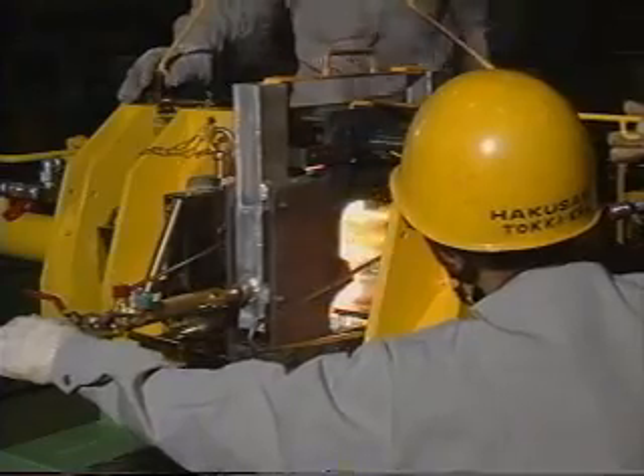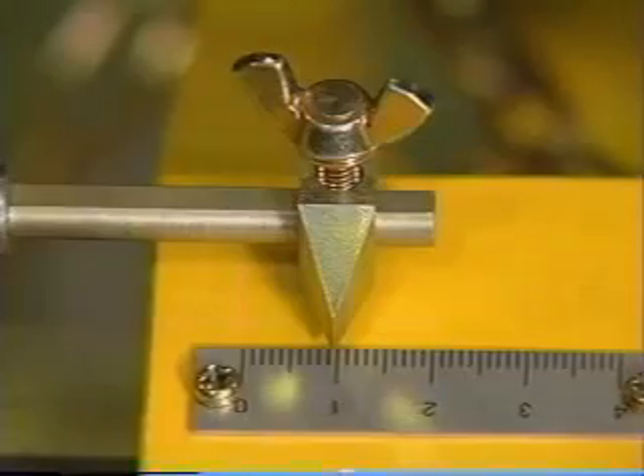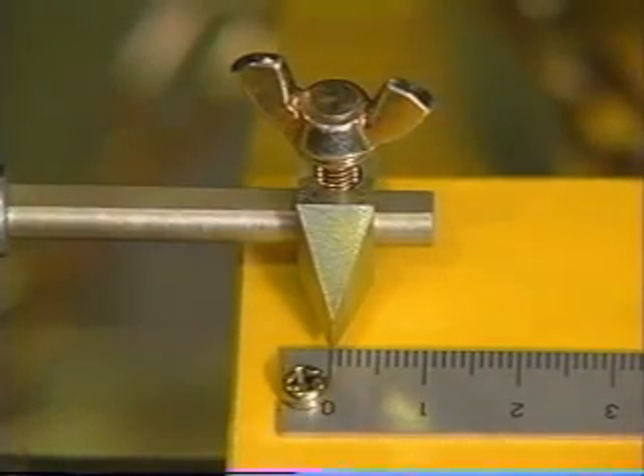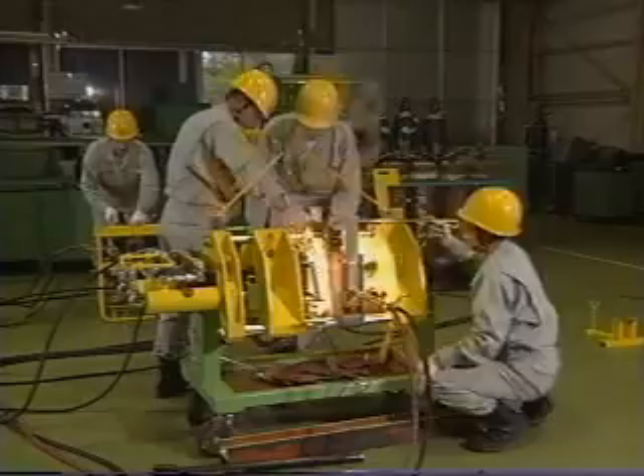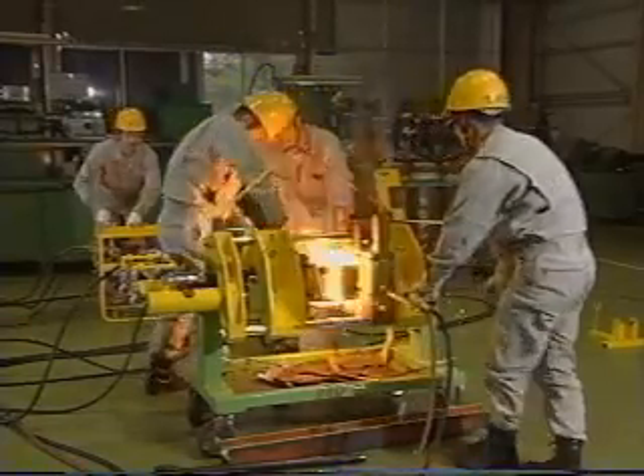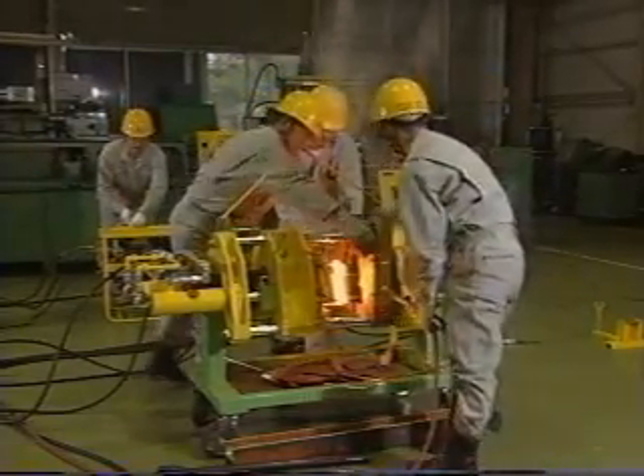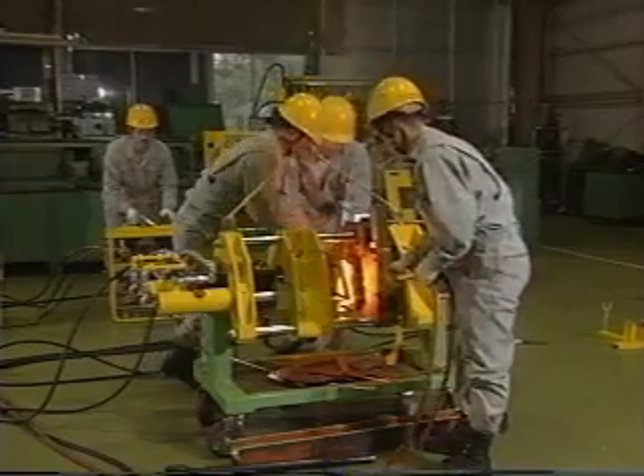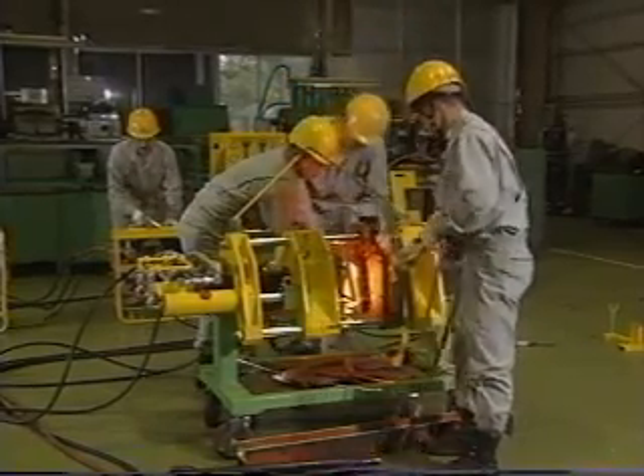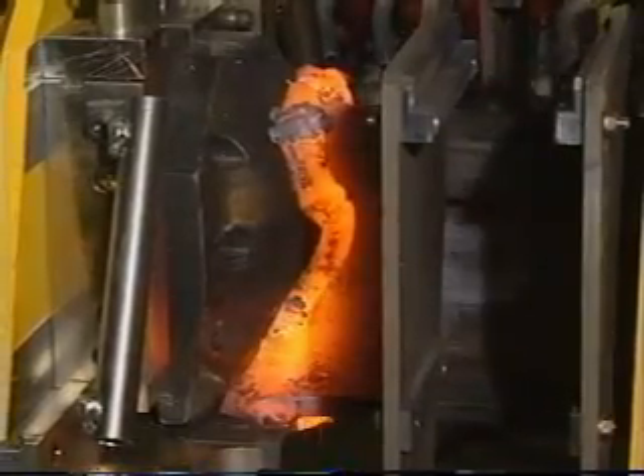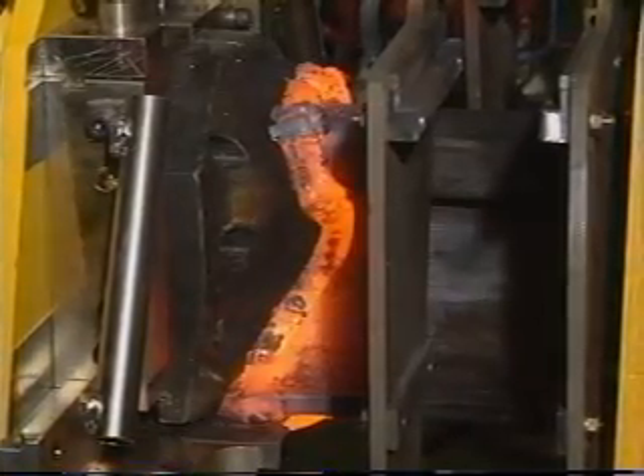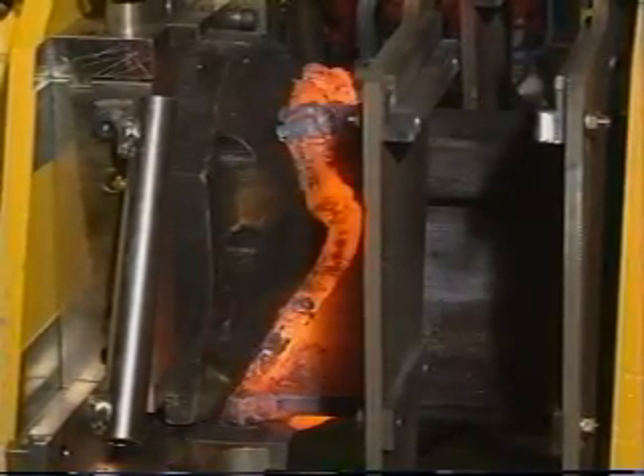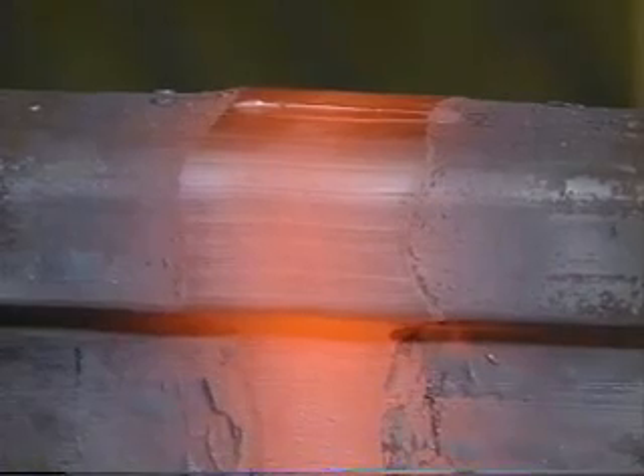Atoms of two rails at the contact face are mixed through the pressure and heat. Crystals are generated at the bulge where metallic bonding is achieved. After checking that the gauge reaches the prescribed welding line, the upset part needs to be immediately trimmed to get a smooth rail surface. You want to shear the bulge while the rail is red hot.